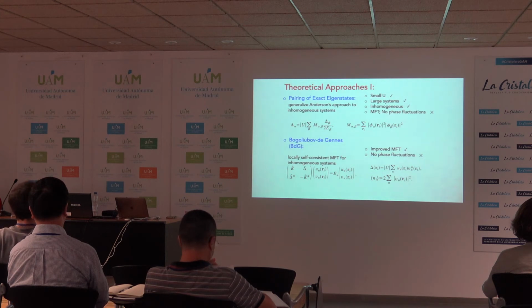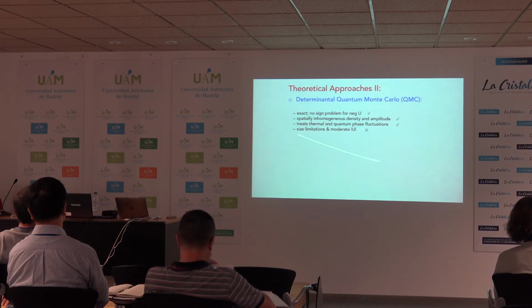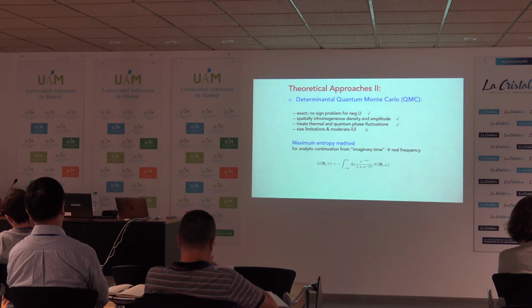Remember I said the order parameter was complex. Those fluctuations are not included. So in the ground state, when you have a superconductor, the phases are all aligned. So we can include that in Monte Carlo. And what is important is you have two kinds of phase fluctuations. As a function of temperature, of course, the phases will fluctuate thermally, but even at zero temperature, you can have quantum fluctuations, and both of those are included in Monte Carlo. And furthermore, we would like to not just get the Green's function in imaginary time, but to compare with experiments to get these density of states and spectra as a function of omega.